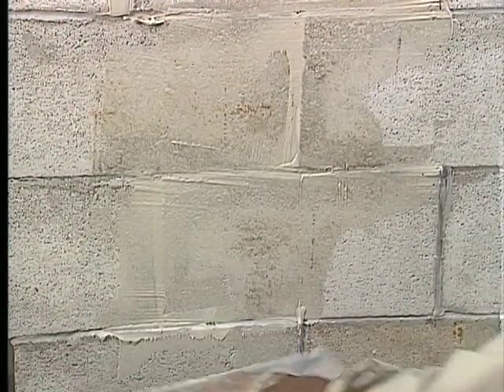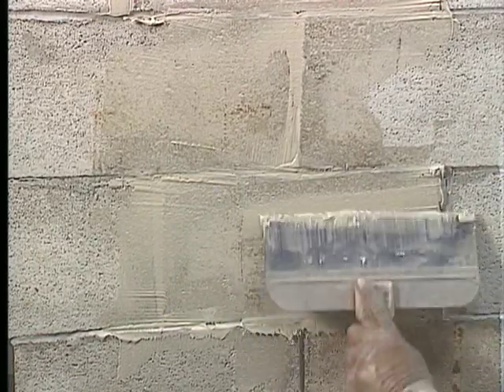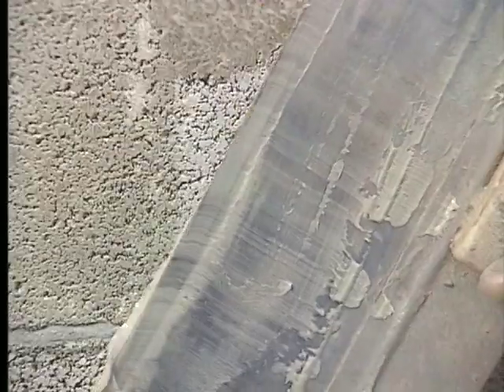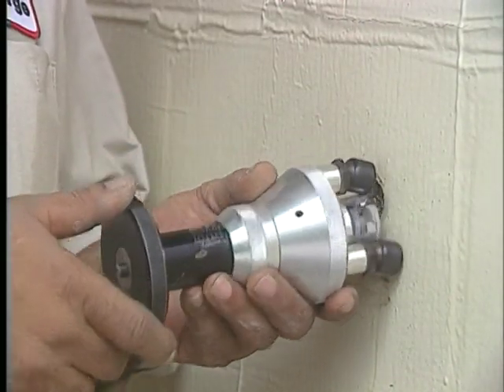If a perfectly smooth wall is required, use ICO Gel vertical epoxy paste to smooth out joint lines. 1 or 2 coats of ICO Gel, sanded, will give you a perfectly smooth wall. ICO Gel can also be used for filling bug holes in concrete walls. For old painted walls, remove previous coats of paint all the way down to bare block. If this isn't possible, remove all that you can and test the remaining paint with an Elcometer adhesive tester.